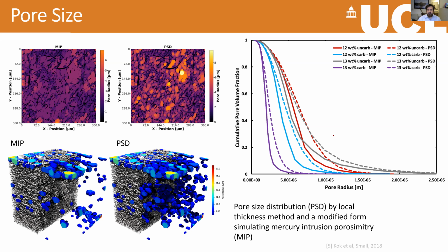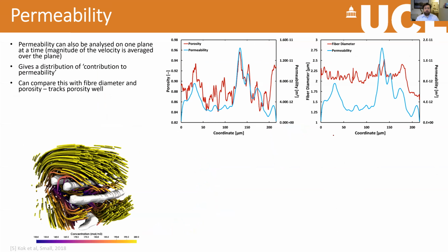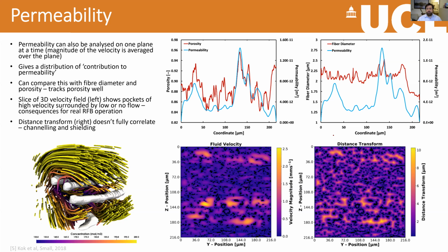A key thing here is actually using modeling to model this permeability. This allows us to do things that we can't actually do with experimental conditions. We can actually look at sort of localized permeability and look at these areas of inhomogeneity within the electrodes, which are really key to how the flow batteries work, and also key to things like degradation as well.